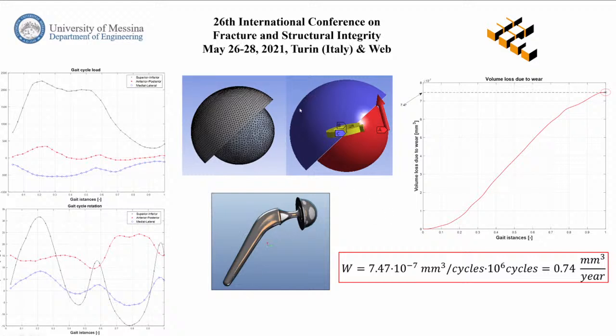And also in this case, we build a finite element model. So as you see here, we consider the load condition and the rotation condition. And through the Archard law, and obviously using the exponents that we found through the calibration, we evaluated the total volume lost due to wear. Obviously, in this case, we considered only one instance, and we reported these results to 1 million cycles, which corresponds to 1 year of gait, and we obtained this result that, compared with literature results and clinical studies, is in very good agreement with other research. Thank you.